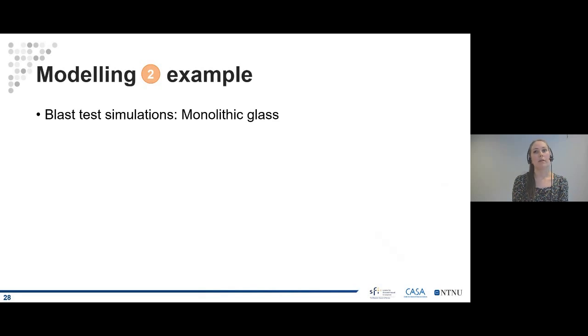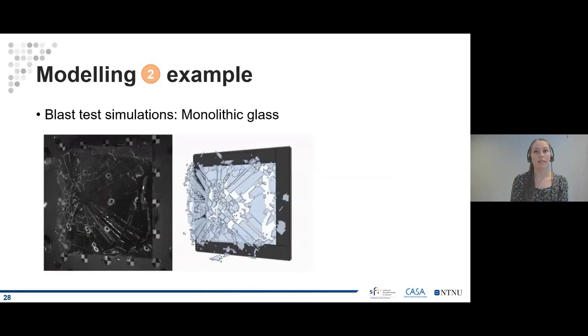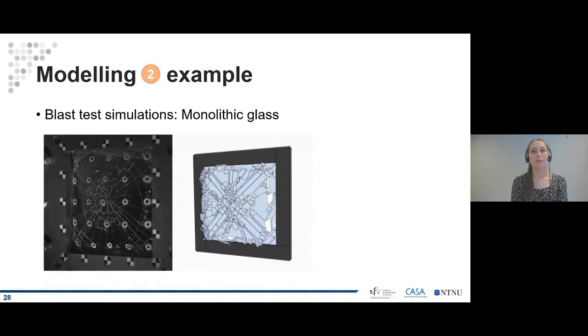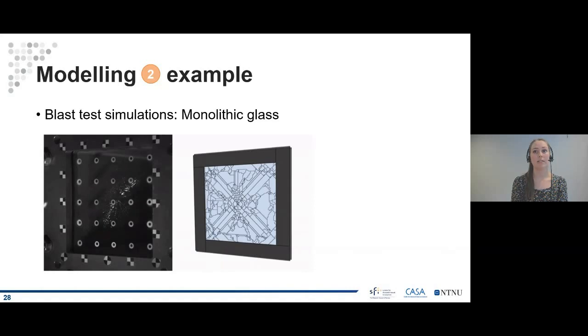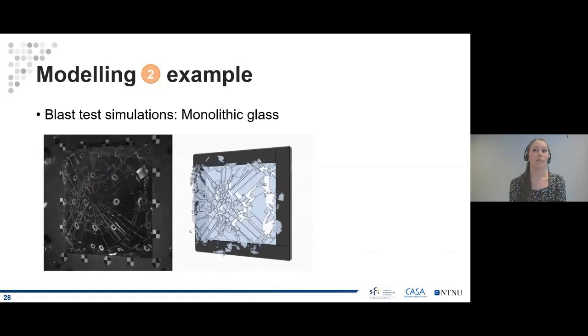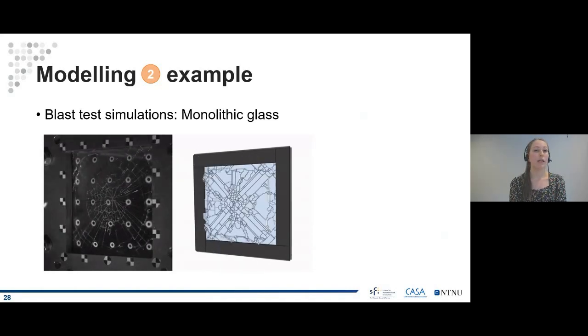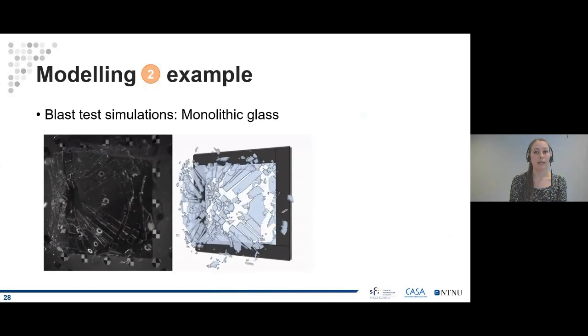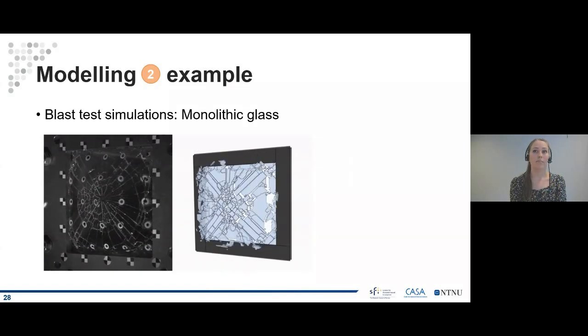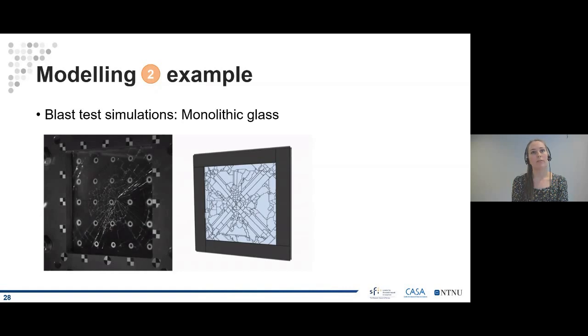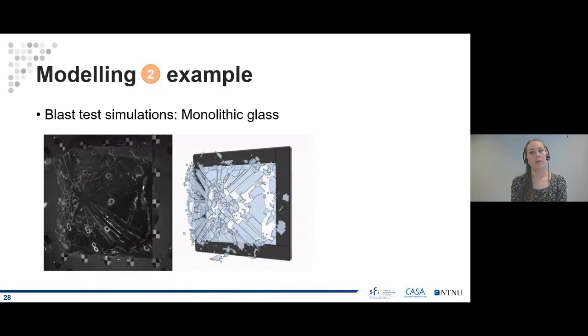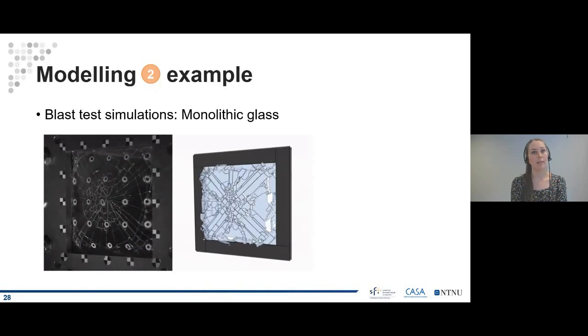Then I will start off with the monolithic test, and I have only included a qualitative comparison between the simulations and the tests here. So here is the video. We see here that the simulation recreates many of the mechanisms that we saw in the experiments. We get crack branching from the initiation point, and we are also able to describe these long and very large free-flying fragments.